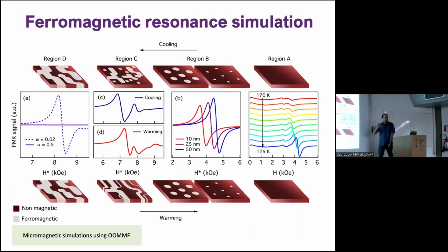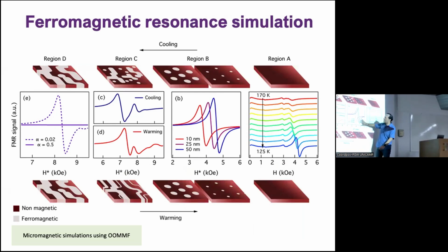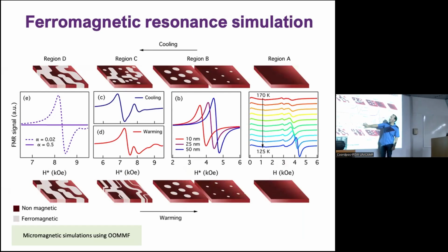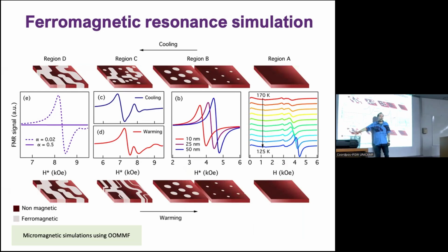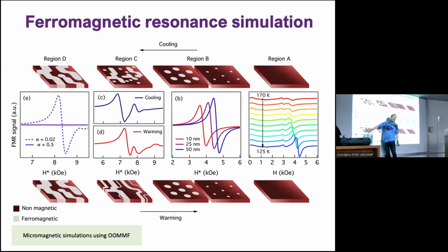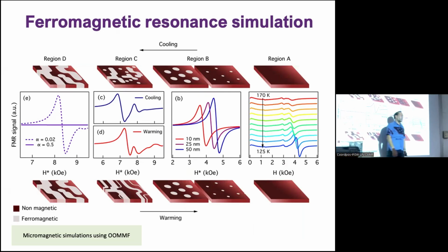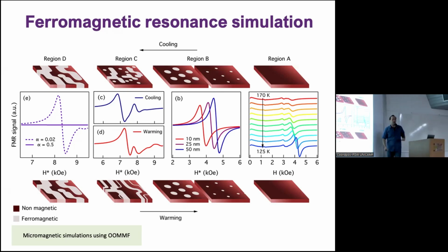This is the simulations. So this is our own simulation where we actually, when we grow the domain size, we shift the resonance field. If we account here for percolation paths of the ferromagnetic domains, those percolation paths, those domains, will give you several resonances, sometimes 2 resonances. And then here, because the sample is very metallic, then if you include the damping into the simulation, then you can actually decrease this by a lot. By just changing 1 order of magnitude the damping, you can actually kill the whole resonance. Okay? And this is what we think is happening.